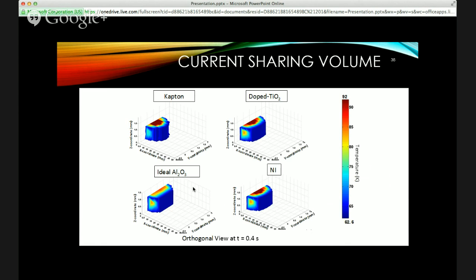So outside of that, what you can see for Kapton is you have more thermal energy in that central conductor. So if you think of that left boundary as where the hotspot initiates, and then going along the x-coordinate, it would be going along the length of the actual configuration itself. So you see that it's moving fast within that central area, which is what normally happens.